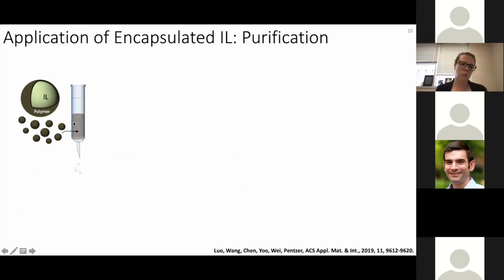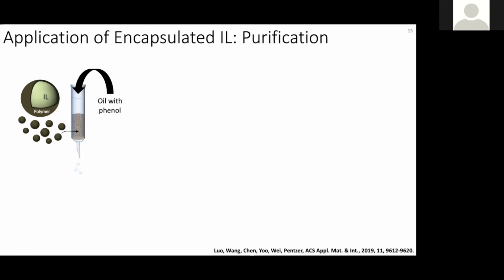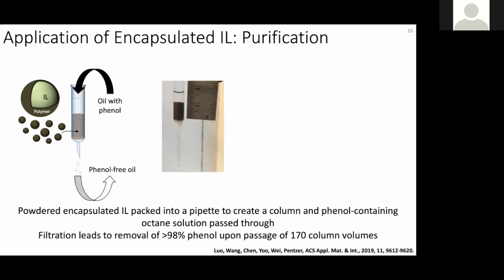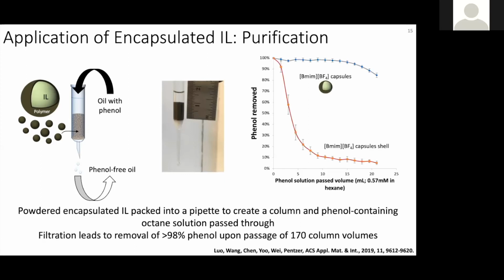But here Yifei and Chinmo took the capsules and loaded them into a column with the idea that we could then pass oil that had been contaminated with phenol through the column, and the phenol is soluble in the ionic liquid, so it would go through the capsule shell, and then the eluent would be that phenol-free oil. And so we compared the ionic liquid filled capsules to the capsule shell by itself. Here's a little pipette column that they made. And basically we see that we are actually making use of the ionic liquid upon encapsulation. You could also envision using the polymer chemistry of the shell to control the permeability and selectivity of the removal as well.